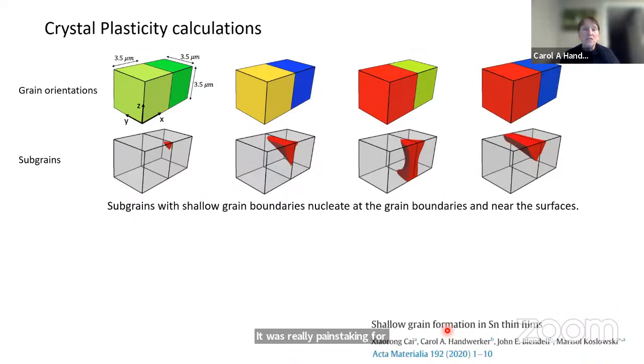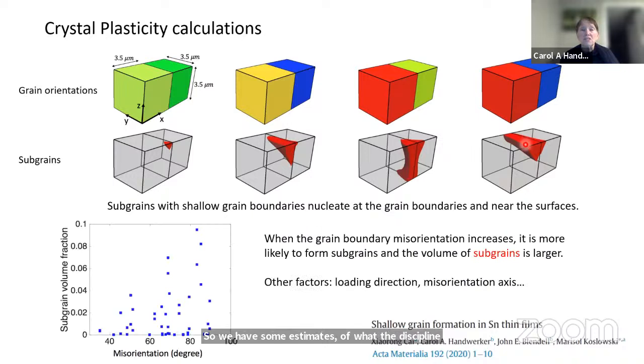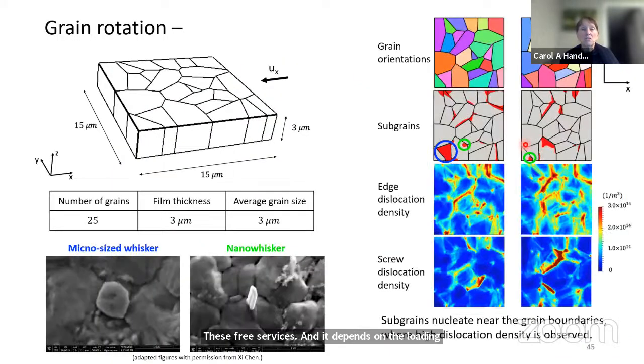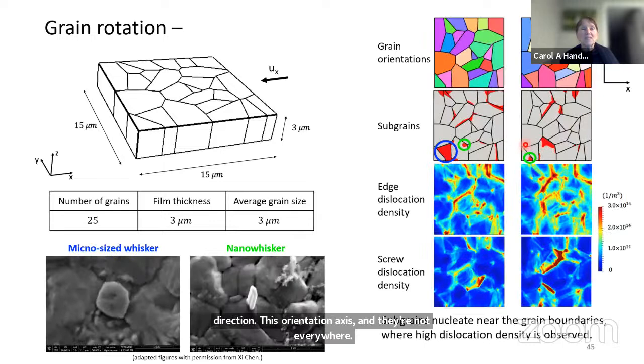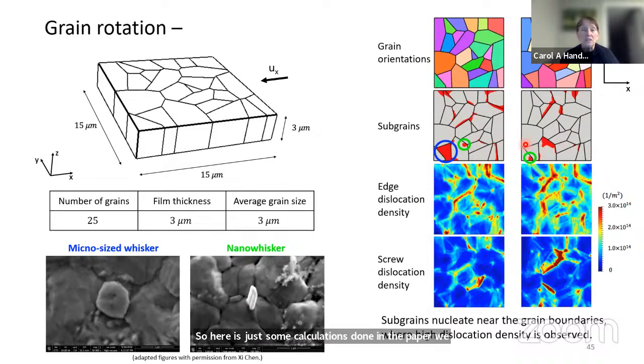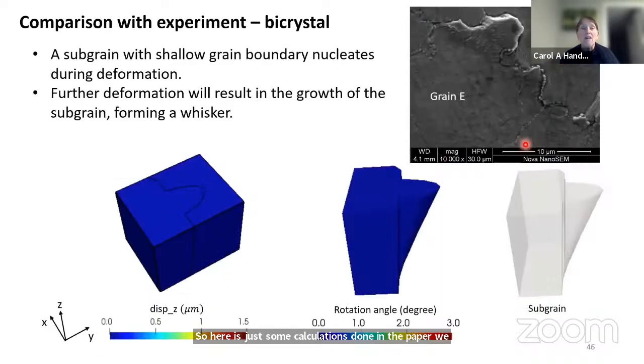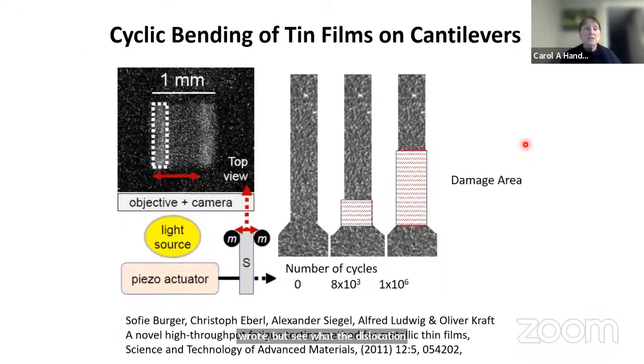So we've also done simulations that show this is where dislocations are accreting depending upon the misorientation. So we have some estimates of what the dislocation generation is near these free surfaces, and it depends on the loading direction, misorientation axis, and they're not everywhere. So here are just some calculations done in a paper we wrote, but seeing what the dislocation densities would be. But I'm not going to go into these details.